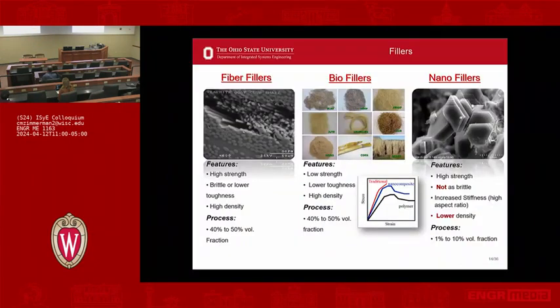So when we talk about these fibers, we're actually talking about different types of fillers. You can have fiber fillers, biofibers, and nanofibers that are introducing these things. They all have different effects that need to be understood. Ultimately, what we measure, for example, in mechanical testing is stress versus strain, which hopefully everybody has seen before. For example, the red material has a higher elasticity, but it also maybe breaks a little faster than another material, maybe the nanocomposite in the middle or maybe the polymer.